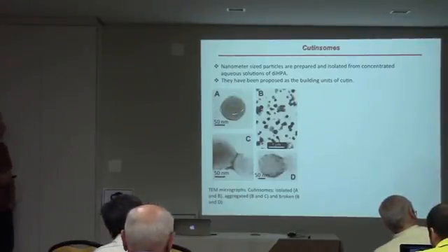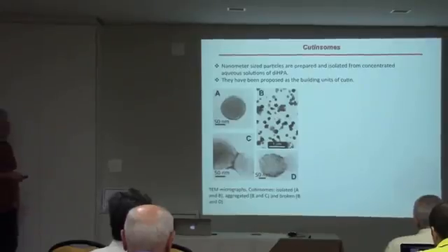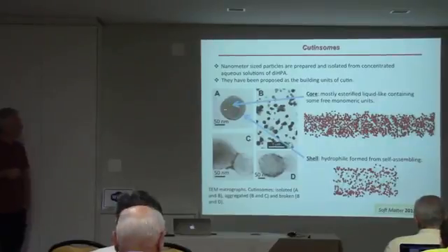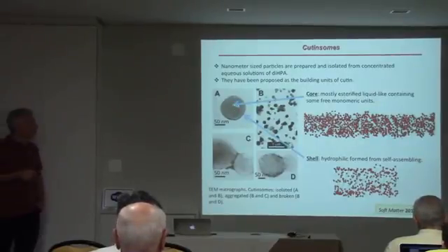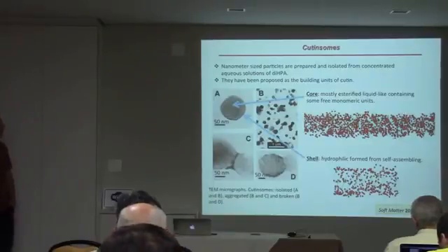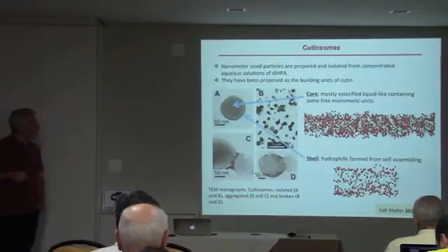They are like a nanocluster that can sinter, forming new larger particles. Simulation also shows the structure of the interior of these nanoparticles, which is mostly esterified liquid-like content, and the shell is a hydrophilic system.